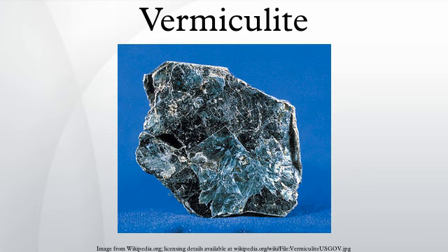Commercial uses: molded shapes. This process involves mixing exfoliated vermiculite with inorganic bonding agents such as sodium silicate and potassium silicate to produce an earth-damp mixture. This material is then hydraulically pressed into shape in a mold, and then heat-cured at temperatures up to 180 degrees Celsius for up to 24 hours depending upon the thickness of the molded part.